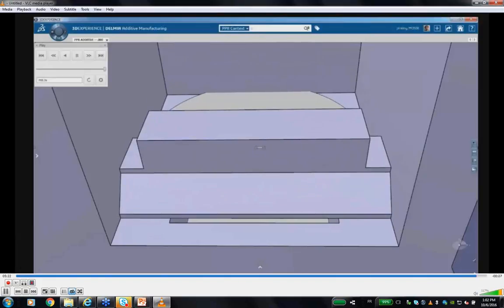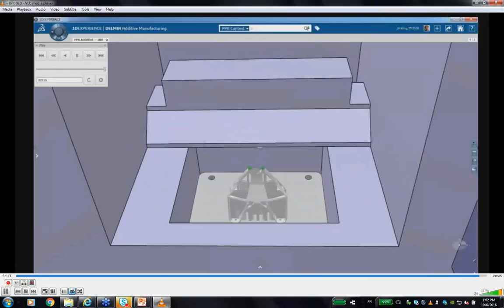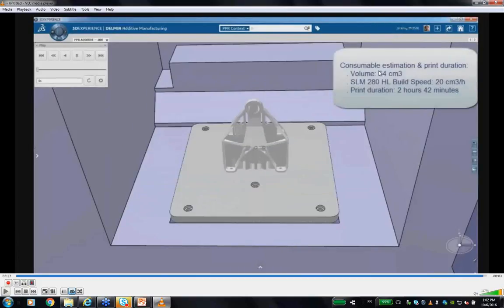And more than that, we can also simulate the process to get now an idea of how much material we are consuming and what is the print time, because those are the two KPI. The cost of a printing process is really depending on those two parameters, how much material I'm using and how long will take the printing. Because as you know, a printing machine is quite expensive, at least so far. It's between 500,000 euro up to 1.5 million euros. And if you use it for 20 hours or 35 hours to do the same part, it's a choice. Okay, so it's important to understand that.